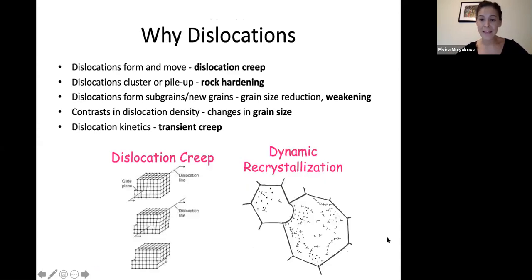Here we go. So first, I'm going to focus on dislocations, and here's why, just to give you some motivation. Across Earth conditions, a lot of the solid rock deformation occurs by dislocation creep, and that involves formation and motion of dislocations. As the rock deforms, the dislocations, which are linear defects within the crystal, may cluster and pile up and explain some of the rock hardening that is seen in particular at colder temperatures. The dislocations are also responsible for parts of dynamic recrystallization, where they can accumulate and form subgrain boundaries and induce grain size reduction, which then leads to weakening.